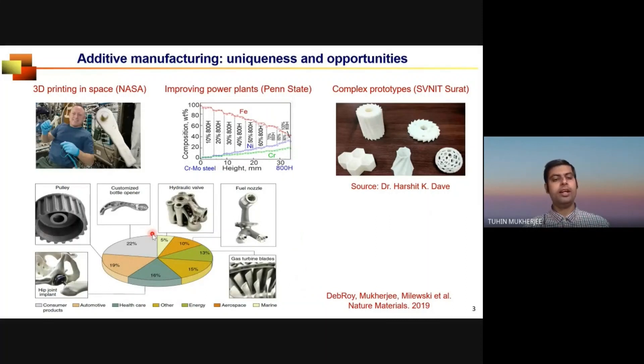At Penn State, we have shown that dissimilar material joints used in nuclear power plants — such as a joint between steel and nickel alloy 800H — are highly susceptible to creep failure at high temperature. Additive manufacturing allows us to replace those joints with graded materials where composition gradually changes along the joint height, which significantly improves creep properties. Revenue from additive manufacturing spans automotive, marine, aerospace, healthcare, and many other industries.